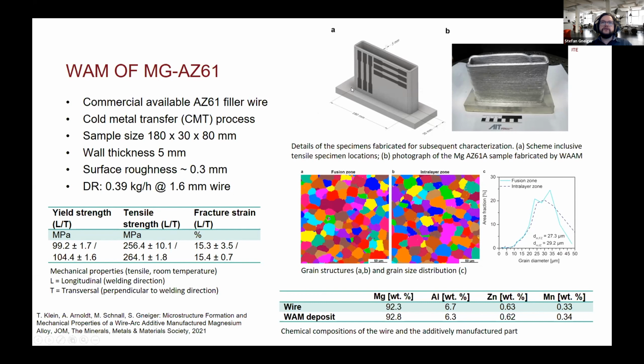Yeah, and we investigated the material properties in the vertical and also in the horizontal direction. So this is the welding direction. Here in this table, you can see the mechanical properties from the tensile test at room temperature. L, so the first number always states the longitudinal, the welding direction, and T is the transversal, so the perpendicular to welding direction values. And yeah, they are quite comparable to what we have seen in the presentation before. We have good tensile strength and good fracture strain, and everything is very comparable in both directions.